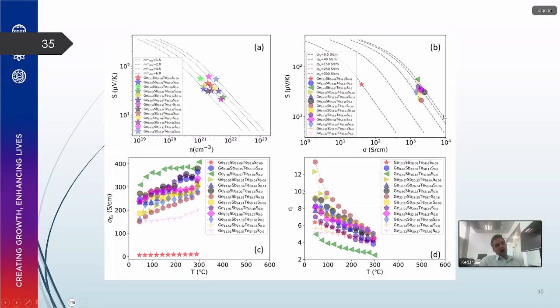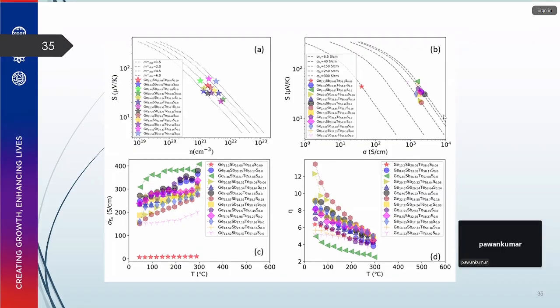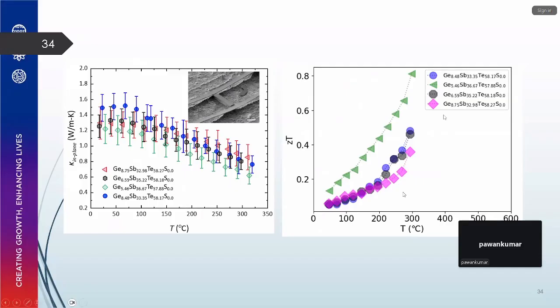Yeah, it's very hard somehow, even though we tried CombiDep and we were hoping for a surprise in a way, right? What does antimony telluride do? Even in the cubic phase, you still get 0.8 at 300 Celsius, much smaller than what you have with the cubic. Compared to bulk, it is still half.